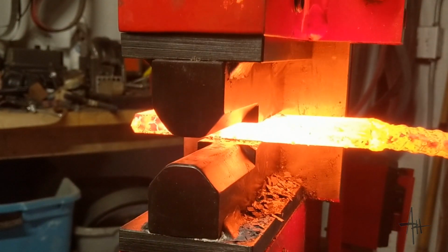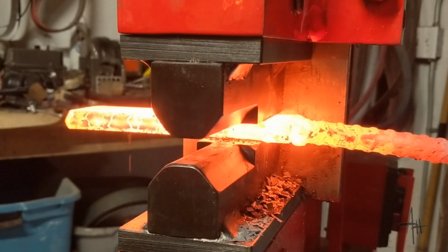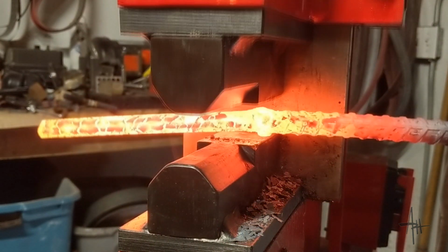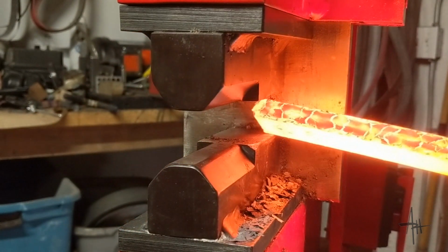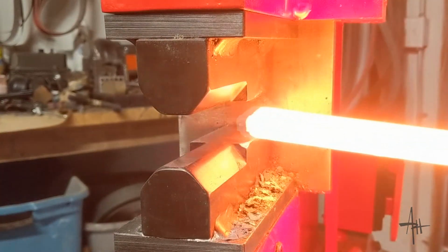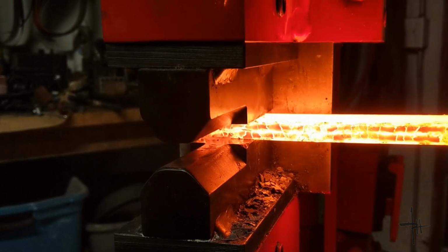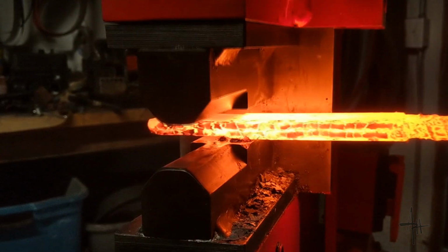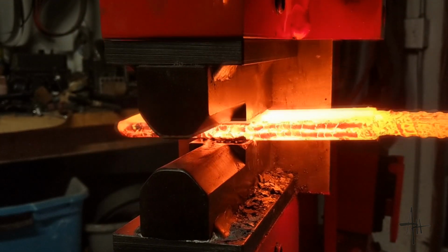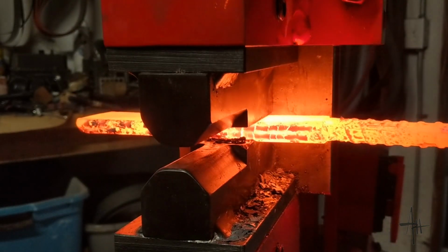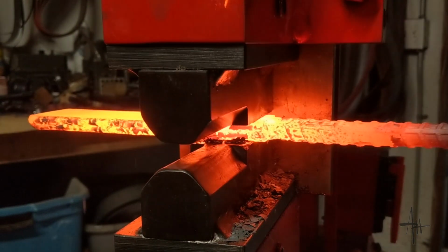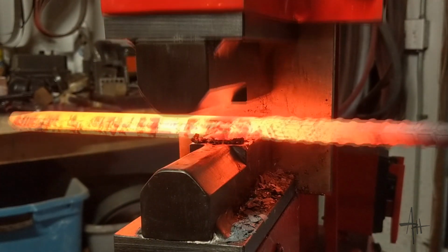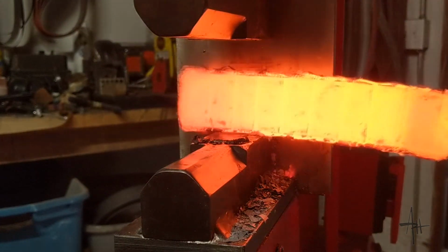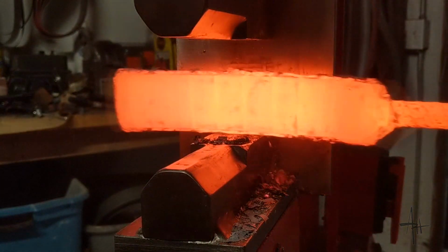And you notice I'm taking very gentle passes on these first couple of welds just to make sure that everything gets set nice. I don't want to overstress it. These materials don't really like to bind, so it takes a gentle touch until you get it fully fused before you start to move it around too much. I also am really careful not to press it on end. One, because the welds haven't been ground off yet and I don't want to press those into the blade edge, but I also don't want to burst any of those welds.